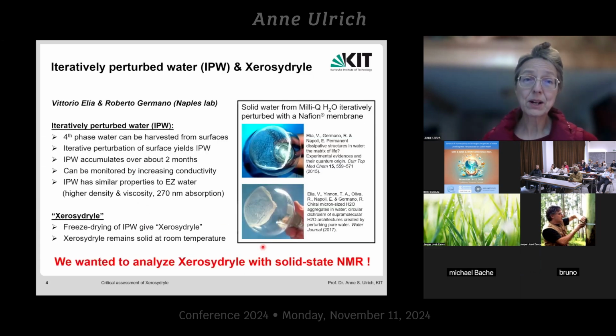And so the idea by our colleagues Vittorio Elia and Roberto Germano, whom I'm just going to refer to as the lab in Naples, is that this fourth phase of water, this exclusion zone water, could be harvested by literally scratching it or gently leveraging it off the surface and accumulating it. This accumulation process can take several months, and it can be monitored, they published, by increasing conductivity, usually by decreasing pH, and they claim that the water that they harvested, the fluid, is similar to what Pollack described as EZ water, has a higher density and higher viscosity and this fingerprint absorbance.